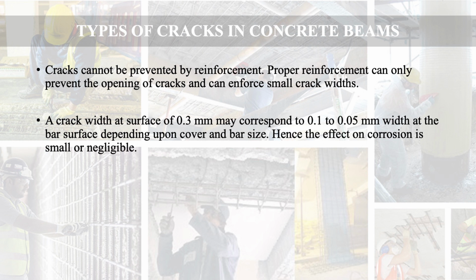A crack width at the surface of 0.3 mm may correspond to 0.1 to 0.05 mm width at the bar surface. It means that a crack having a width of 0.3 mm will have a smaller crack width at the reinforcing bar level, depending upon cover and the bar size. Hence, the effect on corrosion is small or negligible.